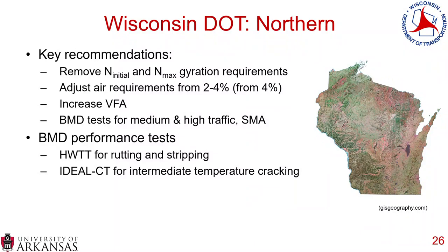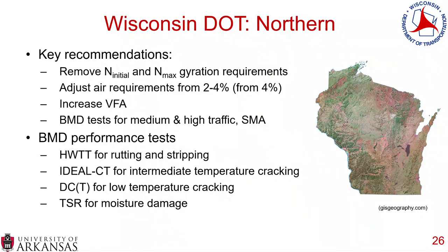The balanced mix design performance test that they recommended was the Hamburg wheel tracking test for rutting and stripping, the IDEAL-CT for intermediate temperature cracking. And I had mentioned that Wisconsin is in a northern climate, so they also included the DCT, the disc-shaped compact tension, for low temperature cracking, and then the TSR for moisture damage. And if you search WHRP, Wisconsin Highway Research Program, 0092-20-04, you will be able to find this report. And again, it's an excellent report, and I recommend that you take a look at it if you are interested.